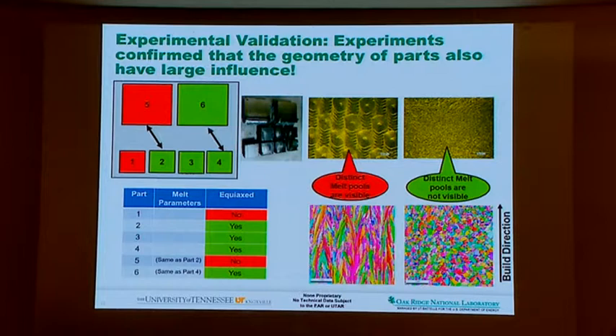If you have a small block and you put a lot of heat, it's going to cool slowly. But if you have a big block and you put in the same amount of heat, it disperses very quickly, like a heat sink, and it went back to higher thermal gradient conditions, so he got back his columnar grain structure. What Narain clearly educated me on is the following: if you are doing additive manufacturing, the processing conditions, materials, and geometry are coupled together. You can't separate them at all. That's what he showed. Now that we understood this, we started pushing the boundaries of this idea into other areas, where we can change the thermal gradients.